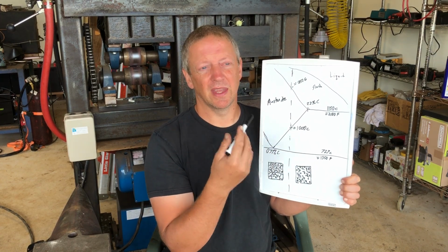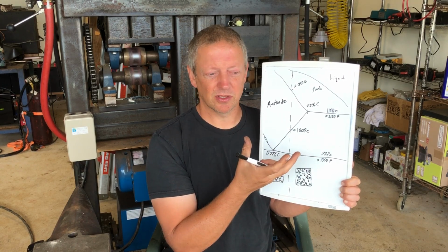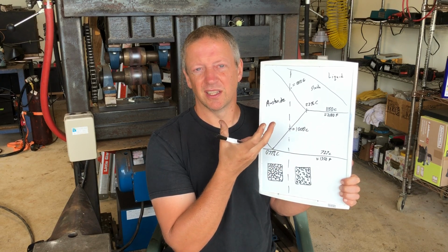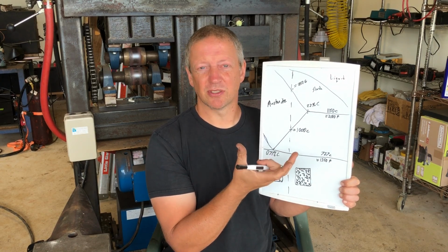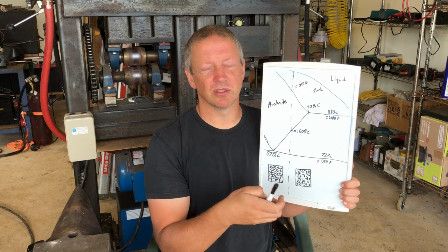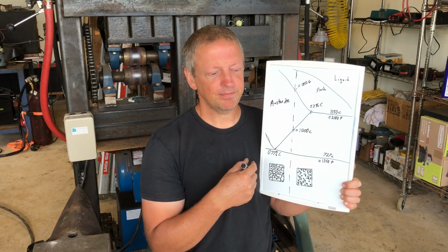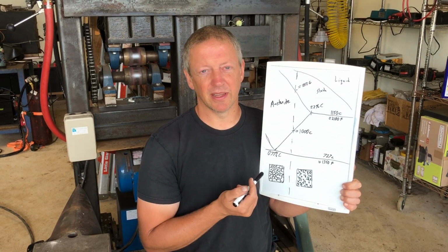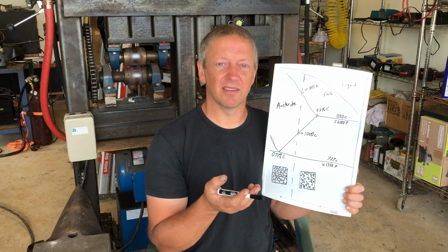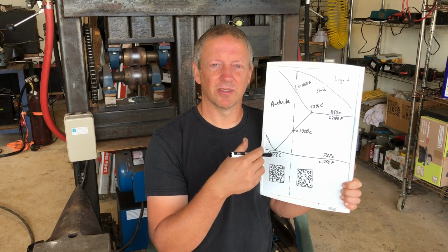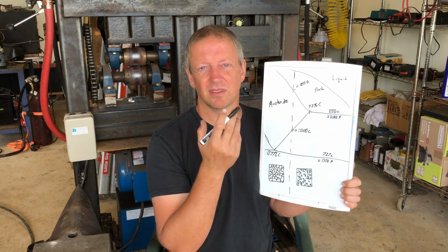In their early work, they did what they called a rim treatment, where they actually decarburized a shell on the outside of the ingot. So they had a low carbon shell on the outside of the ingot to improve the forgeability. Later on, they discovered that wasn't necessary as long as they did not have sulfur and phosphorus in their ingots at elevated levels.